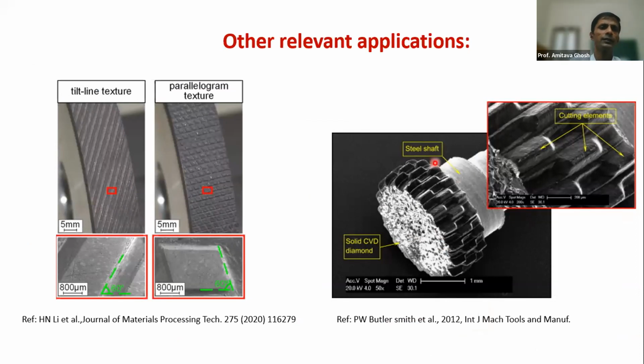So you perhaps know that there is a rigid bonded tool, a rigid bonded wheel, whose surface can be textured in a very nice manner with the help of the laser, very fast, very efficiently. And this kind of texturing is very necessary because the wheel during the grinding has to accommodate the chips. Not only that, it has to make the cutting fluids work very effectively. Otherwise, in grinding, because of the very intimate contact, the efficacy of the grinding fluid is not always properly realized.